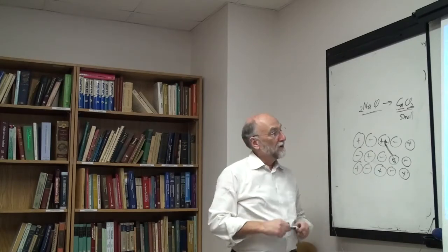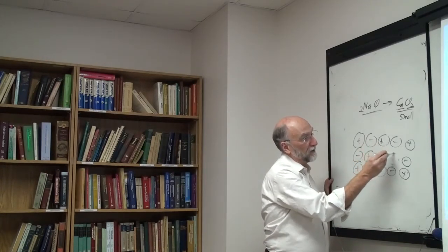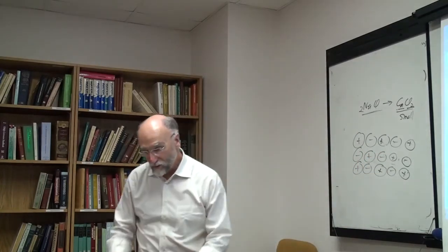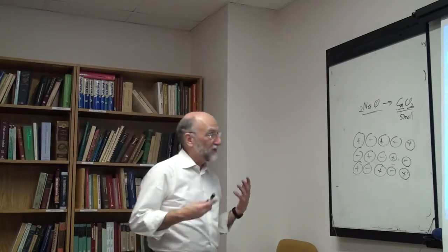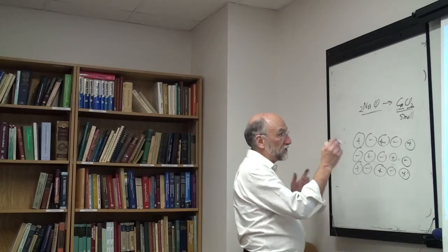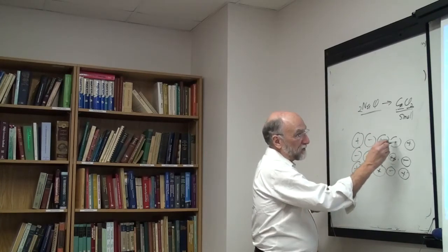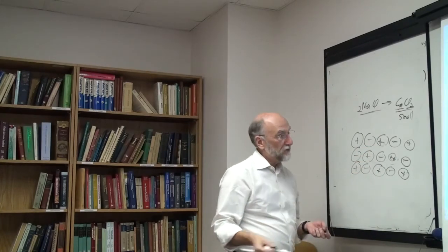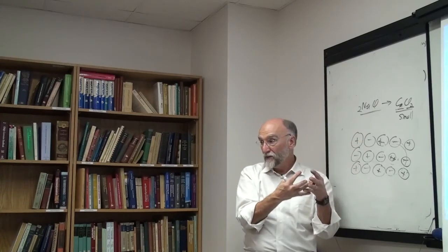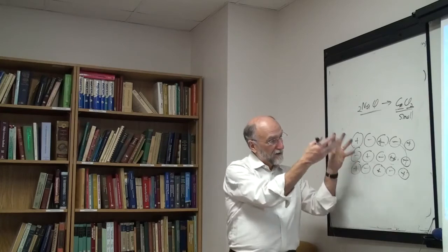So every time you add a calcium, you're really adding a calcium and a vacancy, so you're adding double the entropy. Now if you take a liquid, however, there are no vacancies in a liquid. Well, they used to think there were, but there's no evidence for vacancies in a liquid. What happens when you add calcium chloride to sodium chloride is the calcium replaces the sodium, the chlorines replace the chlorines, no vacancies are formed, and simply locally around the calcium the coordination number changes a bit. The liquid is labile, it can accommodate.